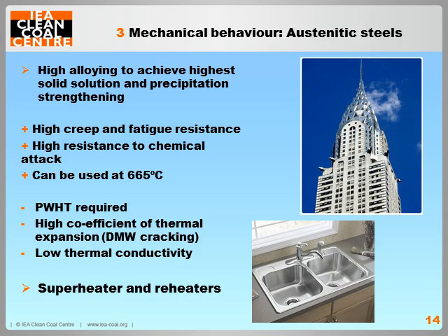Austenitic steels are used in superheaters and reheaters of ultra-supercritical power plant. They're seen every day as stainless steels. High alloying with elements such as chromium and nickel achieve high solid solution strengthening and high precipitation strengthening. They have excellent performance up to around 665 degrees Celsius, but they have a high coefficient of thermal expansion, which results in cracking when used in thick section components. Austenitic steels are therefore limited to thin section components.